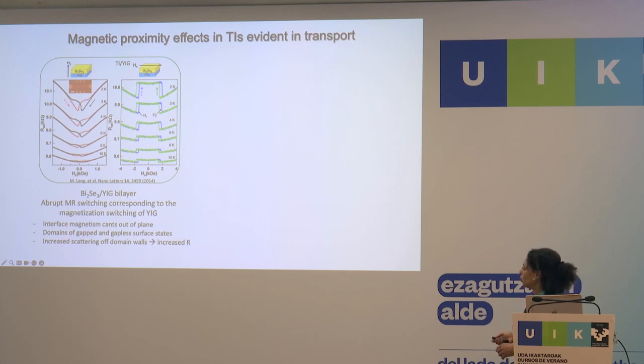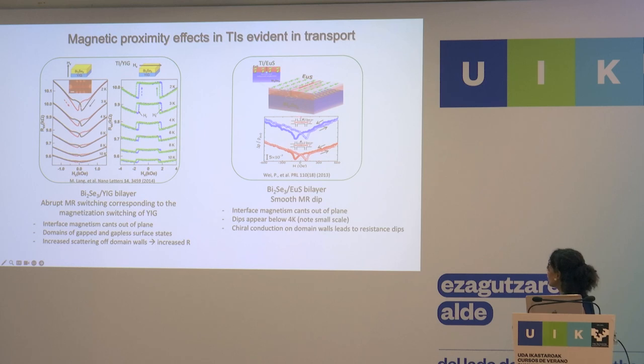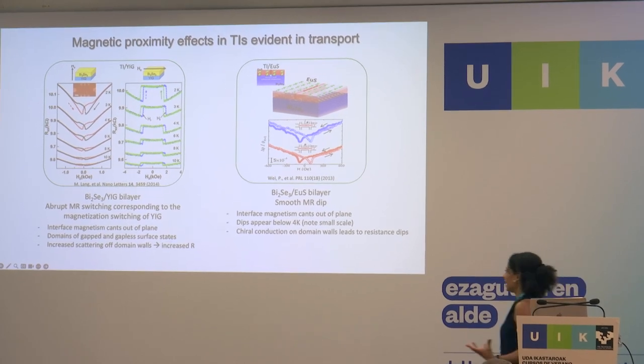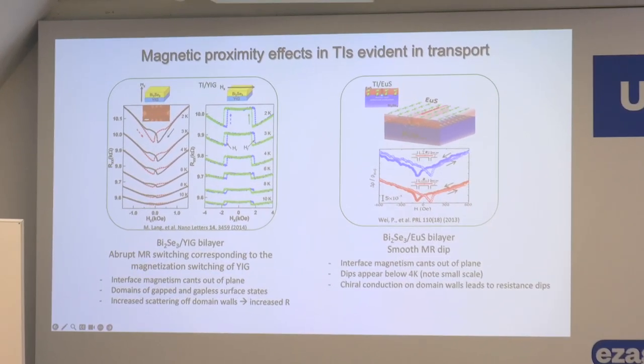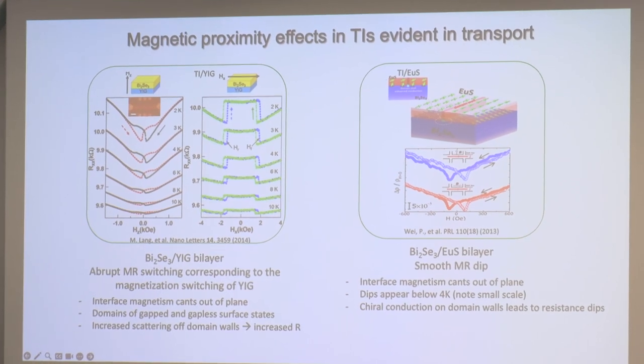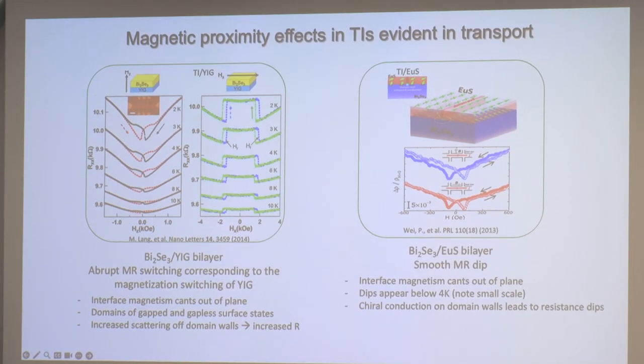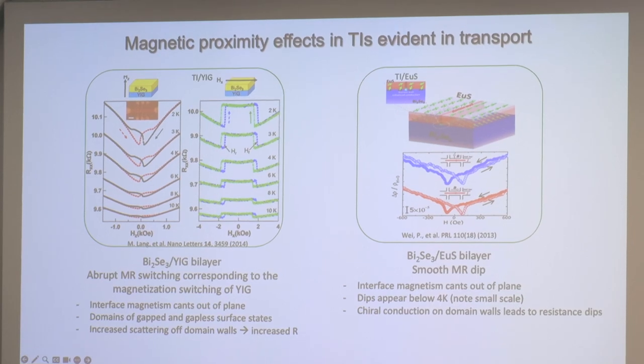These domains are created when you have a magnetic field and you get scattering off domain walls, and that increases the resistance with an in-plane field. But then another paper came out around the same time, and when they put on an in-plane field, what they see are dips instead of peaks. Here they see peaks, and here they see dips for the same field. They also attribute it to domain walls, but said in this case the domain walls led to a decrease in resistance. So there's a little bit of confusion here.